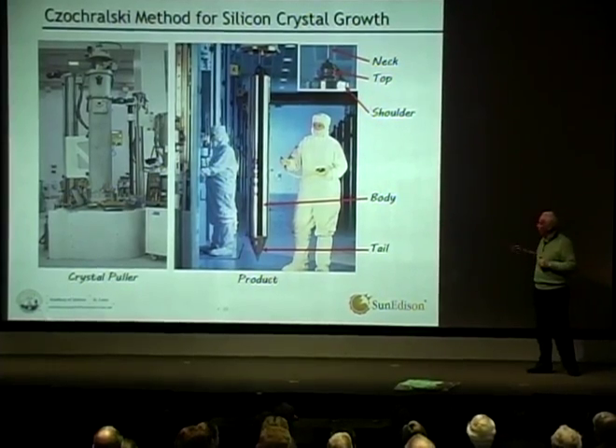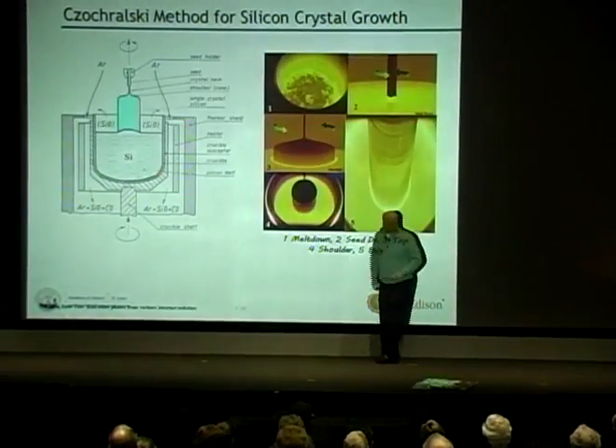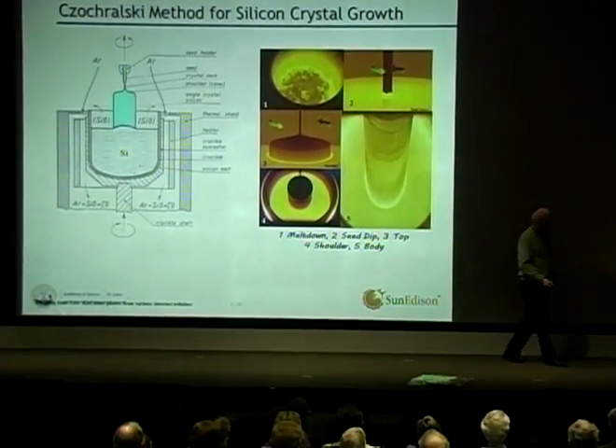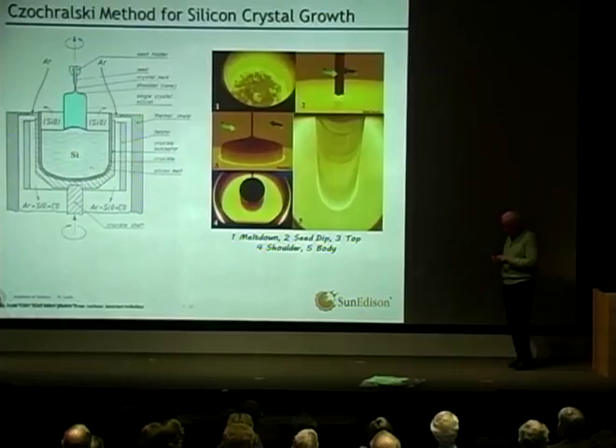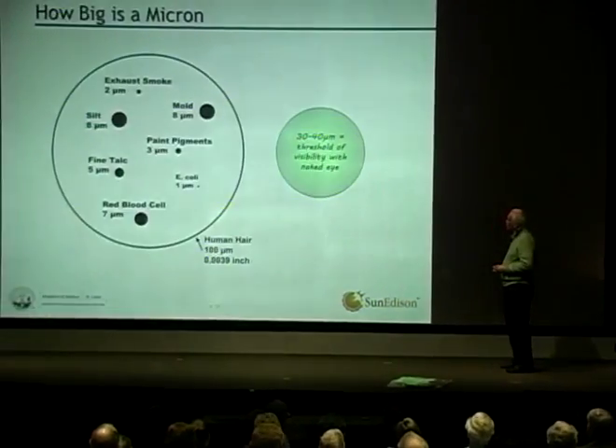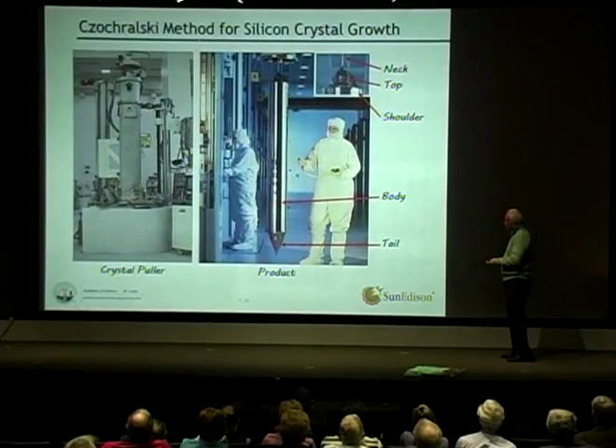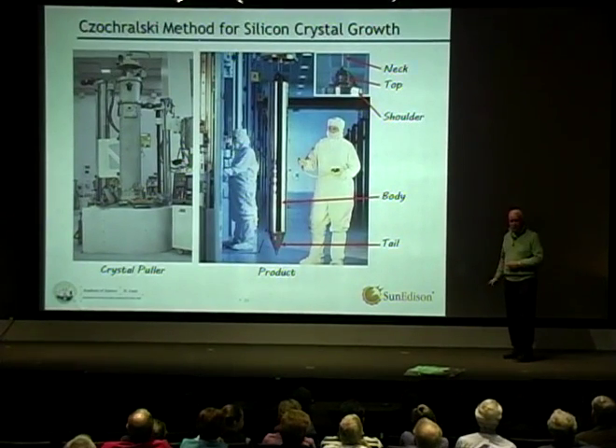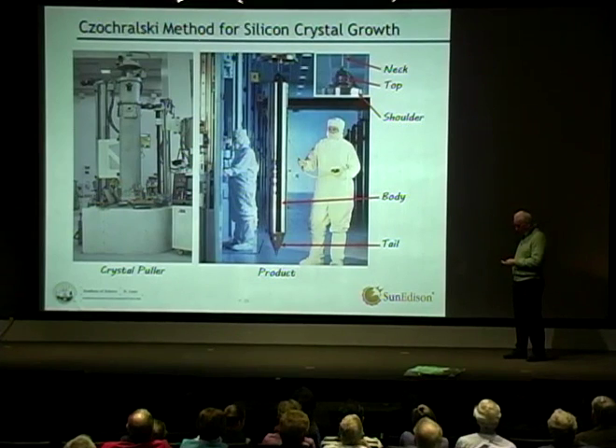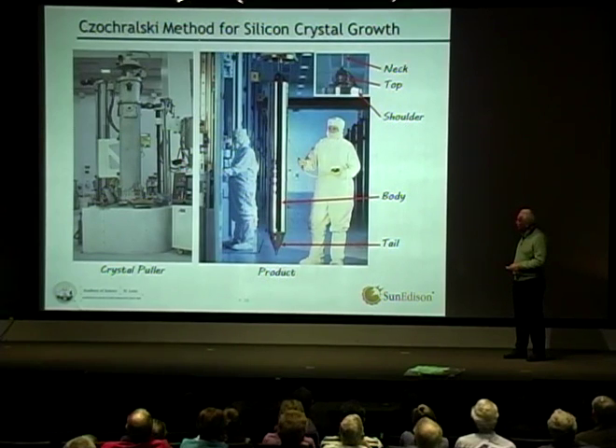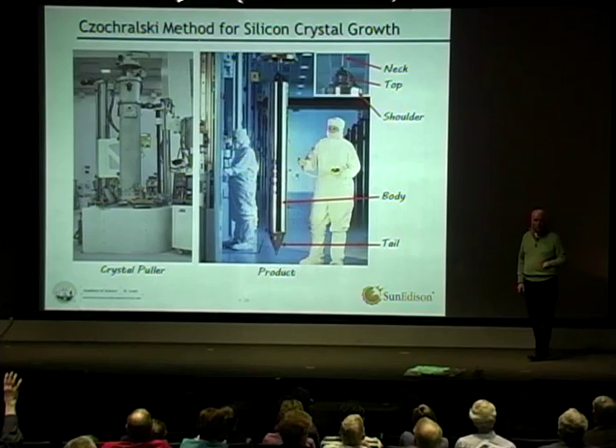So when you create that thermal shock, if I were just to pull it out here, the dislocations would glide back on a 45 degree plane, meaning I'd lose one diameter of the rod. It would have those dislocations in it. So what I do is, during growth, right at the end, I start to pull faster, and then the diameter goes down, and when I pull it out here, it goes back one diameter, but I don't care because it's just such a small distance. And that's why we grow that tail like that, to avoid that thermal shock.